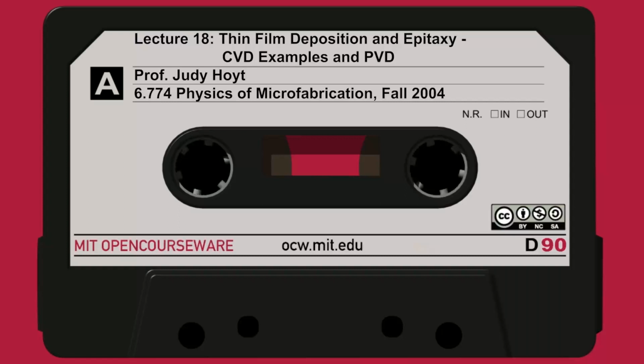Hydrogen can also induce vibrational modes, which can absorb light. So dielectrics put down by PECVD can have much different light absorption characteristics. And finally, the important thing is etch rate. The etch rate of a PECVD deposited film will be quite different from that of an LPCVD film, which will be quite different from that of a thermally deposited film. So depending how you put it down, you need to know what the etch rate of oxide is in HF or whatever. You need to test for that.